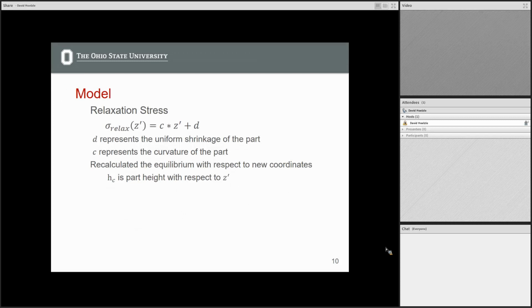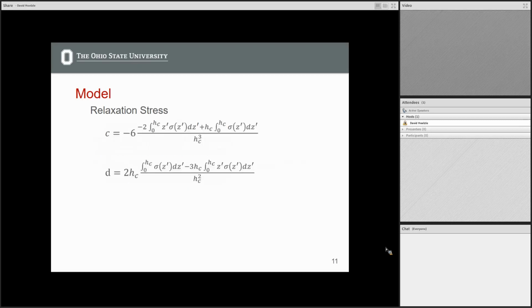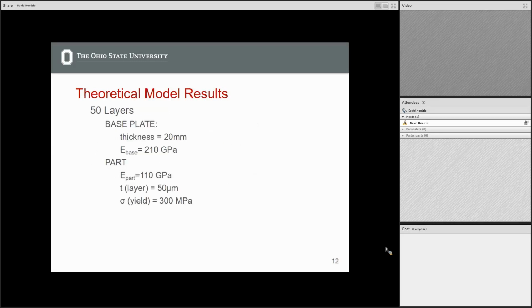So going back to the relaxation stress model, we're going to have a uniform shrinkage of the part and also a deformation or curvature of the part itself. We can solve those two parameters using this equation, which is just going back to the force and moment balance. And then getting into their actual model results, they began with 50 layers with a base plate of 20 millimeters. That's going to be important because they're going to vary the base plate thickness in some of their results, and that's going to have an effect on the residual stress. Their base plate was stiffer than their actual part material that they were printing. They're going to have a layer of 50 micrometers, and the sigma yield, which is going to be important for the graphs, is 300 megapascals.